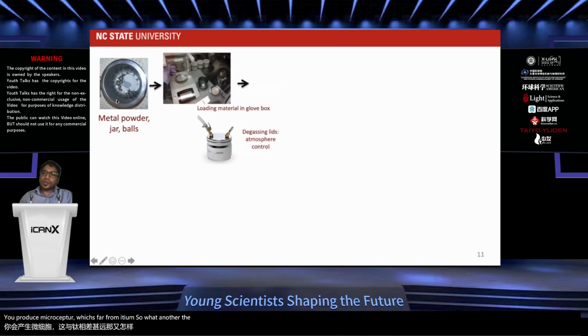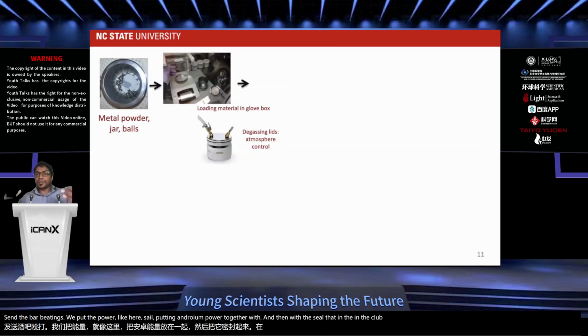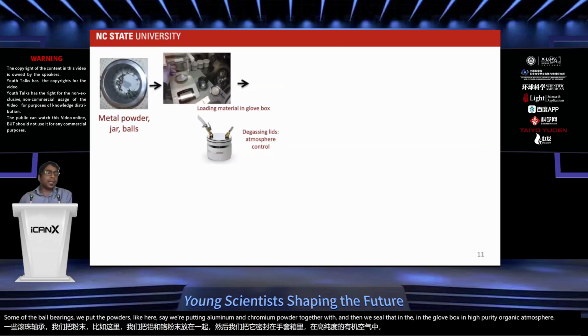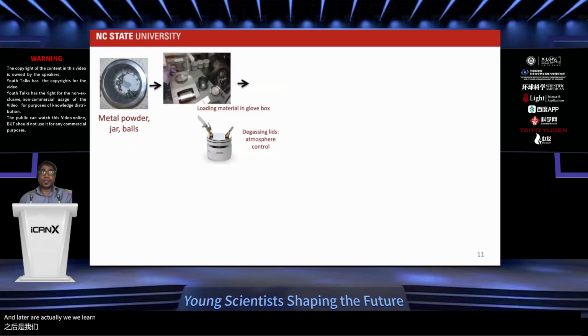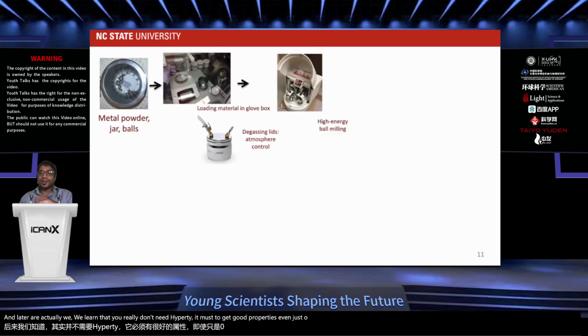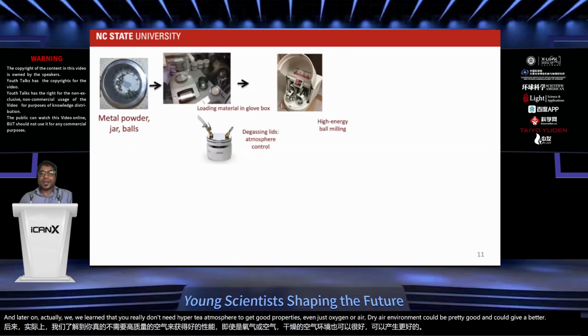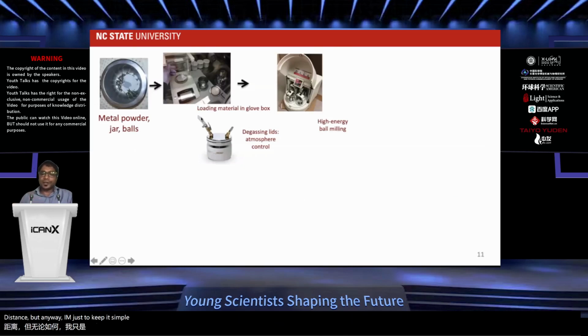One of the techniques could be ball milling. We take a jar and put in some ball bearings, and put in the powders, say aluminum and chromium powder together, and then we seal that in the glove box in a high purity argon atmosphere. Later on, we learned that you really don't need a high purity atmosphere to get good properties. Even just oxygen or dry air could be pretty good and could give better corrosion resistance. But anyway, just to keep it simple, we try to control the atmosphere. So it's high purity argon, put in the ball mill.